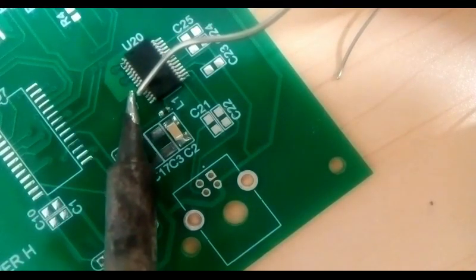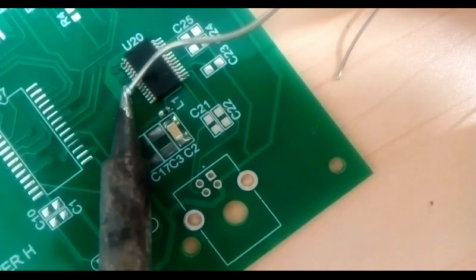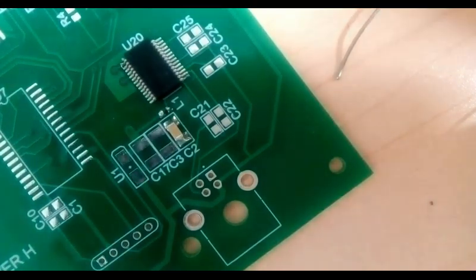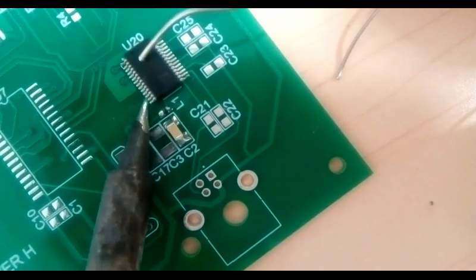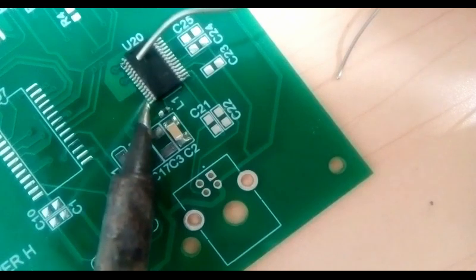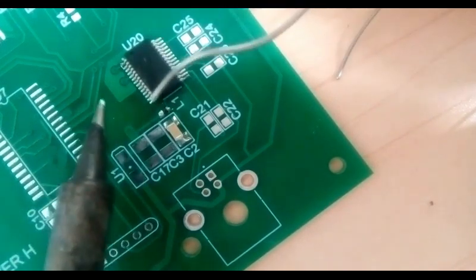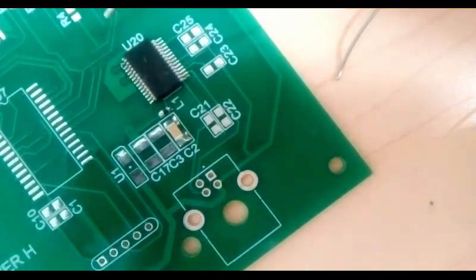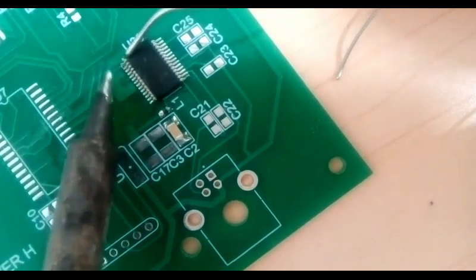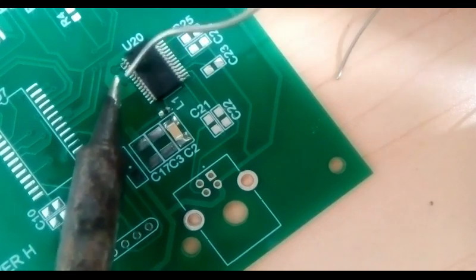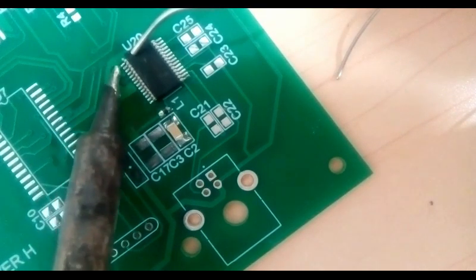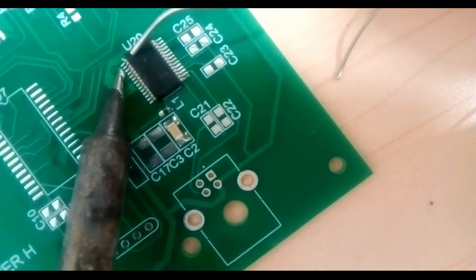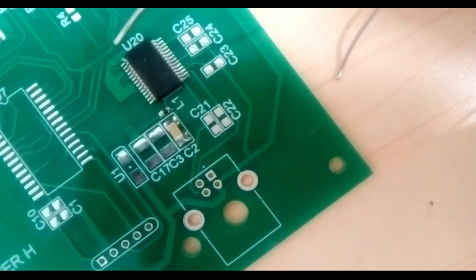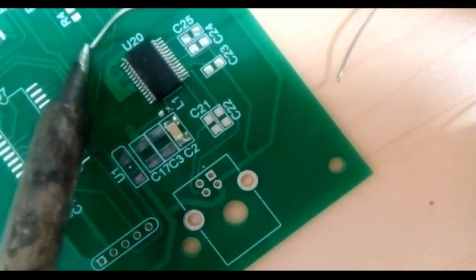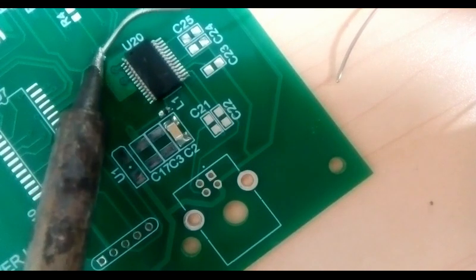And if we've got enough flux there, we should see when we load up the soldering iron with a little bit of solder, that was too much, we can roll in a small quantity of solder into the pin and you'll see it just flow in and get sucked in as the flux evaporates. So we can go and do every single pin. The solder is attracted to the metal thanks to the flux. So very carefully we can do every single pin just by using a little blob of solder.